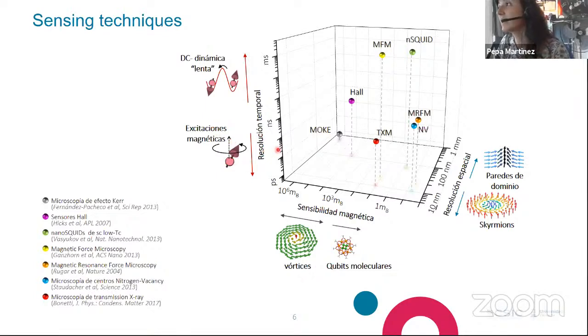One technique that is very often applied to the study of these systems is Kerr microscopy, MOKE, that, as you can see, offers the largest time resolution. It is probably the technique offering the largest time resolution. However, it offers not so good magnetic sensitivity or spatial resolution. Additionally, it is not so easy to apply this technique at very low temperatures or at variable temperature.